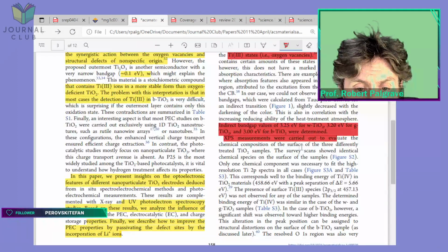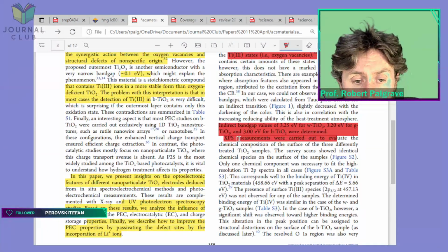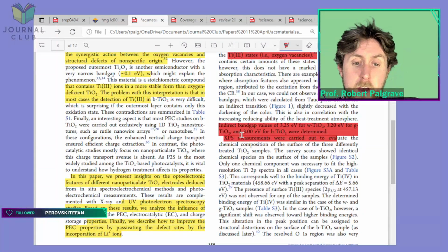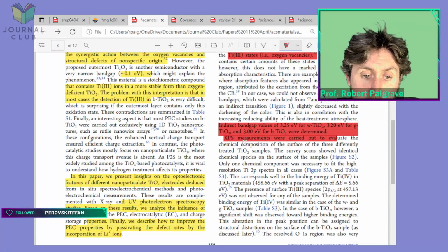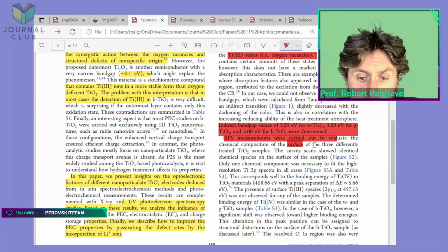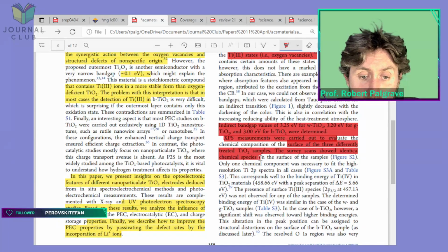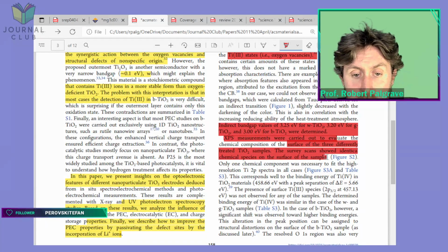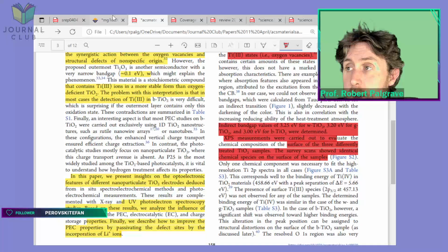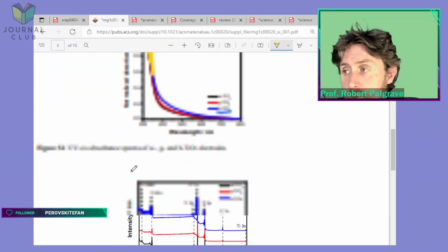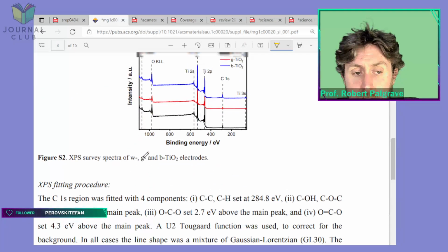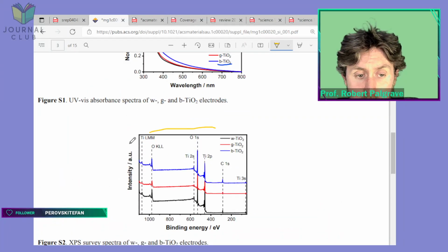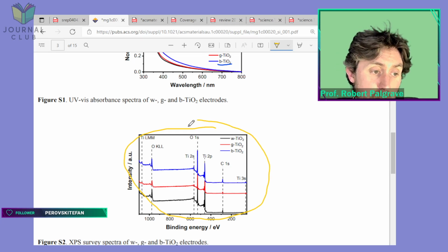The first thing they do is XPS. So XPS is X-ray photoelectron spectroscopy. XPS was carried out to evaluate the chemical composition of the surface of the 3 different treated TiO2 samples. The survey scan showed identical chemical species at the surface of the samples. Let's take a look. Right, on the screen here, this is the survey scan that they are talking about. The survey scan contains different peaks corresponding to different elements.